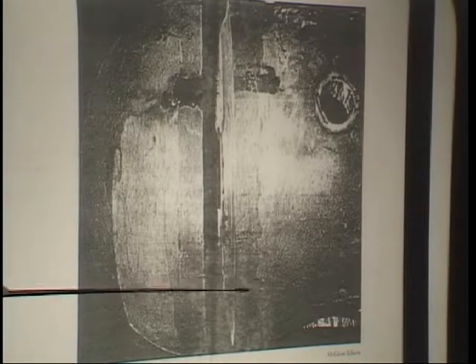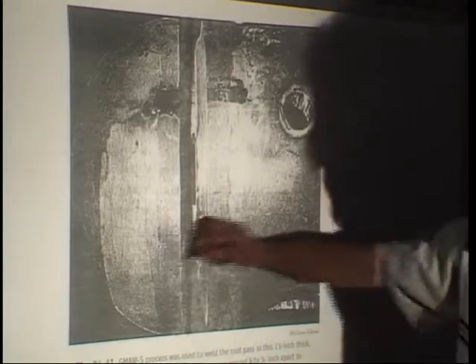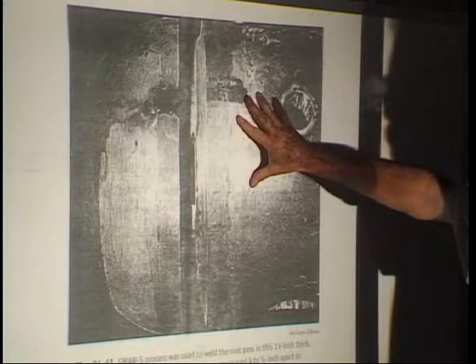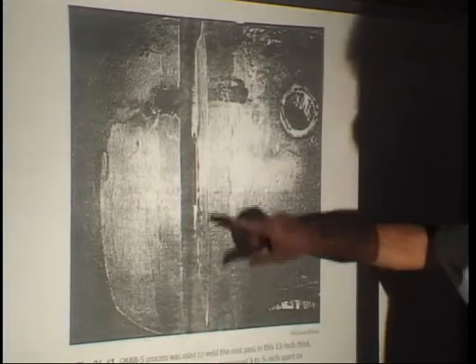I want to show you another overlay, and this is our last overlay, because I just think this is a great picture. Brings back a lot of memories, because I built a lot of this stuff that you're looking at here. Now, this is a heavy wall pressure vessel built to Section 8 of the ASME code, and you can see this is the compound bevel that I talked about before in previous lectures, and you can see how thick that head is. Well, you have to weld a dog on this thing and pick it up with a chain to get it into position, and it usually takes one person to assist you to get that first tack in, and then you'll put another dog with nuts on it, with bolts on it that you'll use a crescent wrench to swing this thing back and forth like a pendulum until you line it up, and you'll use a straight edge then to measure all the way around this to make sure that the head is lined up with the pressure vessel itself, with the body of the vessel, and then you're going to tack it in various places.